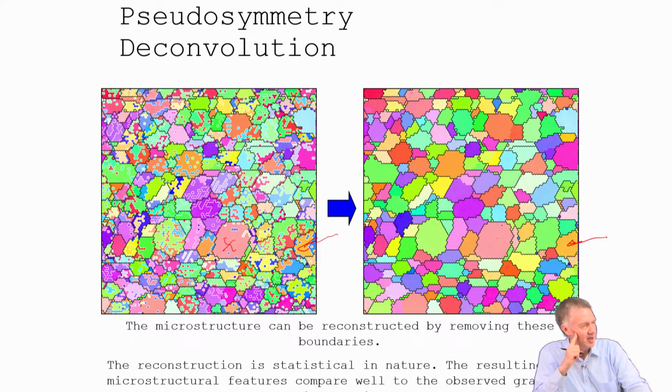So that would be a strategy, just technically how to do it. But as far as in the software itself, the only thing you could do is add more bands, so instead of indexing with 7 bands, use 12 bands or something to index. And then you would have a higher probability of finding that one band that is going to tell you whether it's a superlattice or not a superlattice.